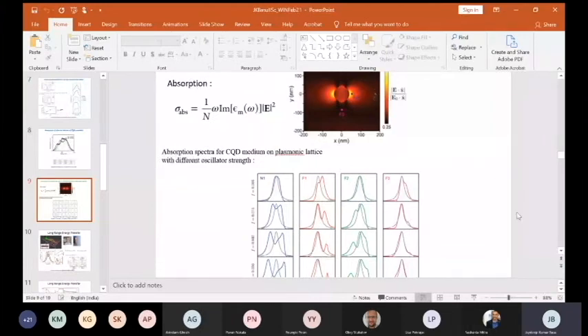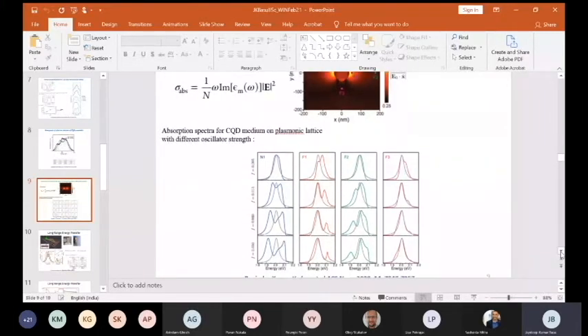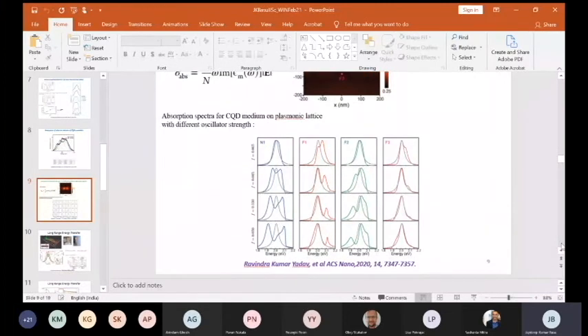What's interesting, to cut a long story short, is that this additional mode, which also appears in the simulations, you can imagine as an effective oscillator strength, but it also represents the concentration. This seems to be prevalent more due to the coupling to this long-range mode. These lattice modes are delocalized, and I think that coupling leads to the emergence of this feature. So this is something which is purely there for the presence of the lattice. If you just took that out and had an individual particle only focused on the near field, you would not see this feature at all, right? So this is the first part.